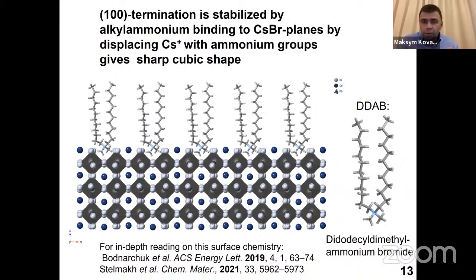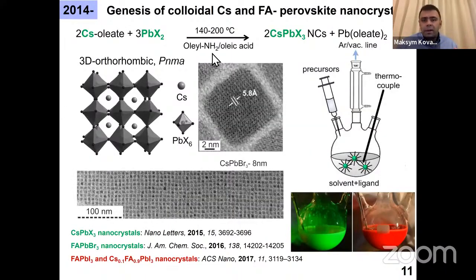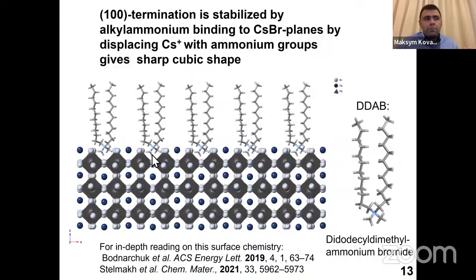And so in our first synthesis, as you might recall from this slide before, we use primary amine, which converts into ammonium, a long chain alkyl ammonium capping ligand. Another example is shown on this slide, which is dialkyl ammonium. So this is an ammonium group, which is positively charged, and two alkyl chains. These cationic surfactants or ligands bind to the surface by displacing the surface cesium ion on the 1,0,0 terminated crystal plane. And so just replacement, let's say, of 50% of the surface cesium yields such a stable